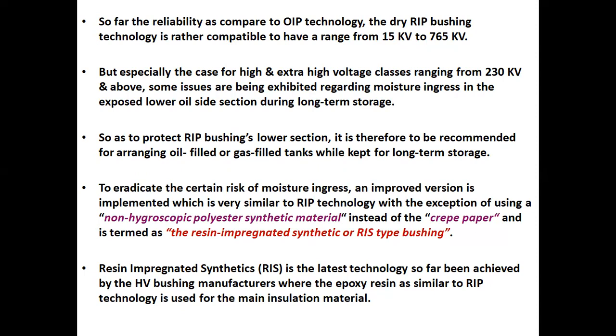To protect the RIP bushing's lower section, it is recommended to arrange oil-filled or gas-filled tanks while kept for long-term storage. To eliminate the risk of moisture ingress, an improved version, very similar to RIP technology, was implemented, with the exception of using a non-hygroscopic polyester synthetic material instead of crepe paper, and is termed the resin impregnated synthetic, or RIS type bushing. That is, resin impregnated type synthetic.